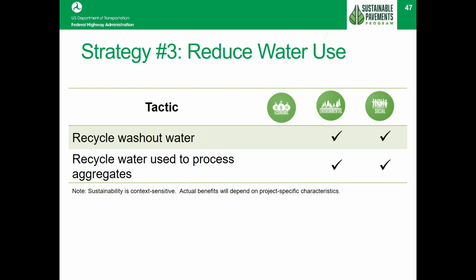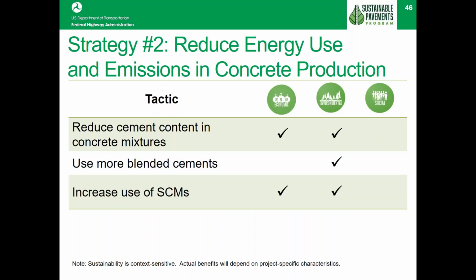The water use is again another consideration. We can use recycled washout water, recycled water used to process aggregates. And going back to the previous slide, just lowering the water to cementitious material ratio itself can result in very significant reduction in use of water. In one case study we looked at, in a relatively small 6 mile project, by reducing the water to cement ratio and increasing the use of supplementary materials, they were able to reduce the amount of water used by 500,000 gallons on that one project alone. So the savings can be significant.